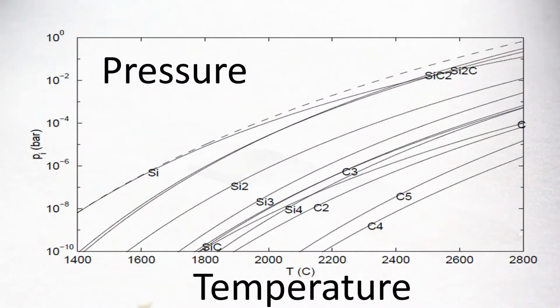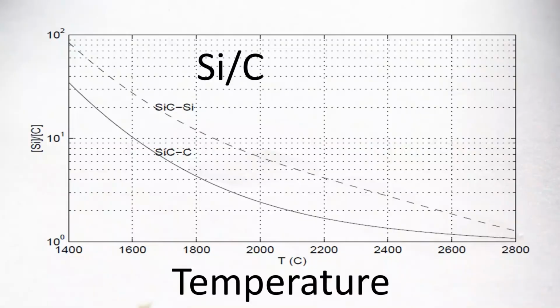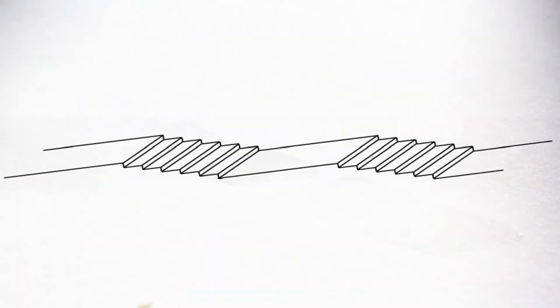And some important things in this context, because it's very tricky to intentionally produce one layer of carbon on the surface. So here you have the vapor pressures. They depend on the temperature. That has an influence on the silicon to carbon ratio, how much shift there is with temperature. And in many materials, you have steps which are formed, and they can form step bunching, which is not good for the growth. But this is also a way, actually, to make the graphene on silicon carbide, because you have the bilayers and then the graphene starts from the edge and so on. So then the steps are very important.